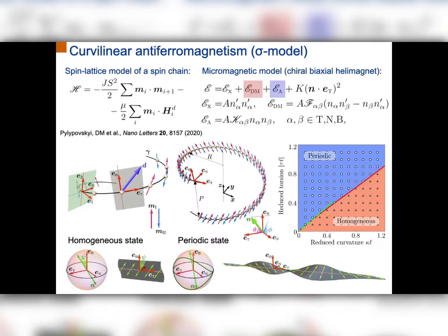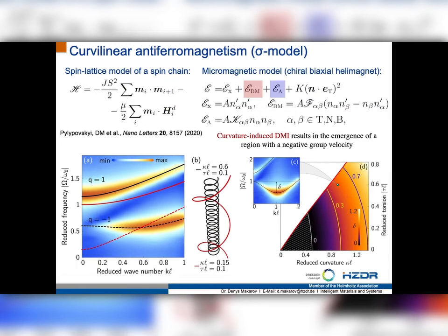You can nicely investigate those types of effects and the impact of geometry on this phase transition. You can analyze what is happening, for example, with the linear excitations on the background of, for example, a homogeneous state. Here you have unexpected effects emerging. For example, for the acoustic branch of spin waves, you can get the possibility to have such kind of